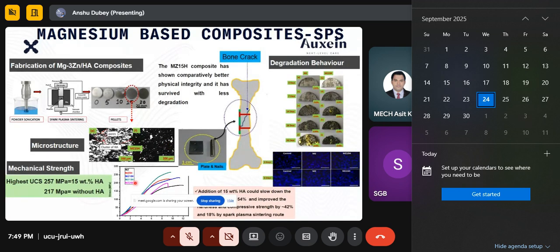Then we did the mechanical strength testing, and it gave very nice results. For 15 weight percent of hydroxyapatite, it was approximately 257 MPa, which was very good news for us. And we tried to develop the plate and pin with the help of the composite. And we did the degradation behavior, and they sustained up to 56 days. And we did the longer degradation behavior also, and six months was the full degradation time for this magnesium composite. We checked the biocompatibility. It was found very good. The cells were growing very fast, and finally we could conclude that magnesium with 15% HA has shown tremendous properties, and there is a green signal that we can go ahead, that magnesium can be used as a medical implant.